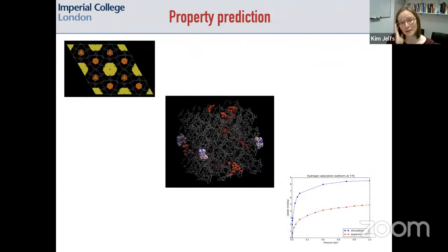So to move on to property prediction, I'm now showing 3 images of property prediction that would be very familiar to people from this community. Generally, if you have a solid state structure for your porous material, you can do void analysis, which I'm showing on the top left. In this case, this uses Zeo++, and the voids are coloured by whether or not they're accessible to a probe of a given size representing a specific guest. In the middle, we can do molecular dynamics simulations, or something a bit fancier than that, ultimately to get an insight into the different diffusion rates of different guests within that porous system, so that you could predict that separation capability. Or finally, you can do GCMC type simulations to reproduce what you would expect to get from adsorption isotherms, and to understand from that capacities, but also potential for separations.